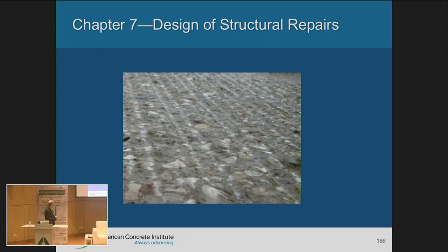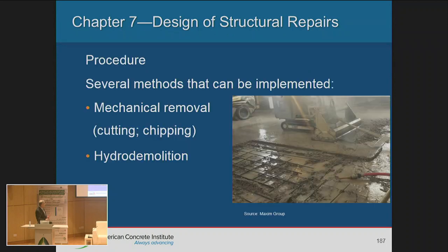And here it shows what the equipment does. For example, here you see the roughened surface, which is top and bottom, because you can manipulate it, you can control it. It's about 6 inches. But one thing with this chipping is that it cuts through the aggregate. So it may create some micro cracking, which is an undesirable characteristic when you have an overlay.